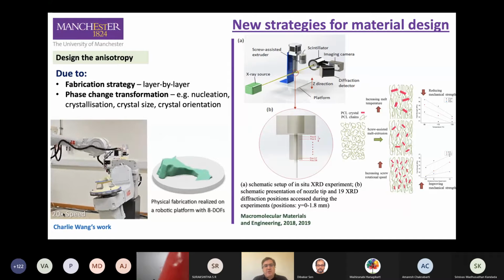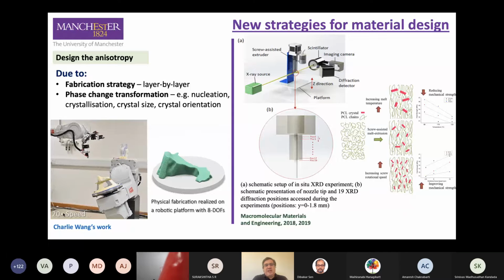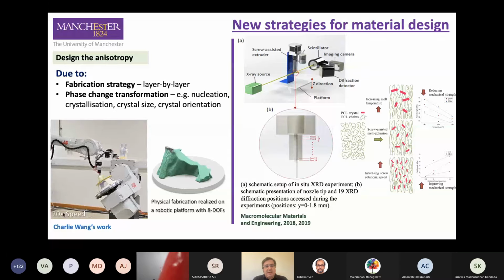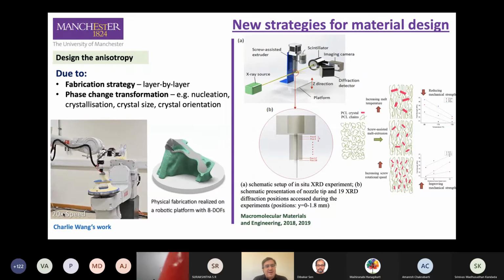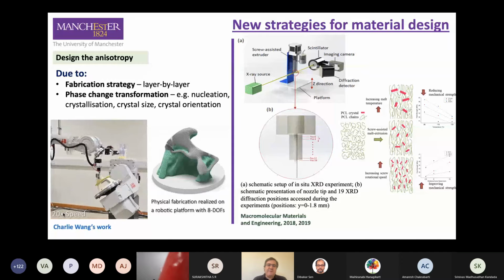In the group, we have a colleague focusing on designing the anisotropy by changing the fabrication strategy, and he is doing this using new lay-down patterns, path planning strategies, together with robotic-assisted additive manufacturing. I'm more focusing on the phase change transformation of the material. And 3 years ago, we ran a couple of tests and we published several papers. I believe that we were the first group in the world investigating the in situ morphological development using synchrotron. And we are developing mathematical models now, allowing us to correlate processing conditions with the morphological development.